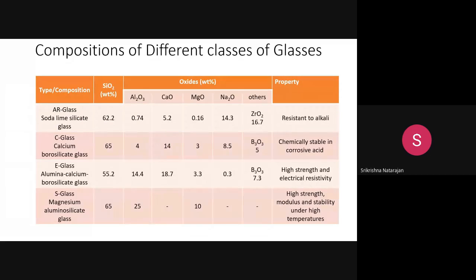And another glass is the S glass, which is called the magnesium aluminosilicate glass. Okay, so here you see this magnesium aluminosilicate. Apart from the silicon dioxide, you have the aluminium and the magnesium. The rest are all absent. So this is for high strength, modulus, and stability under high temperature. Wherever you want to fix a window which should not be easily broken, where high strength is required, in that case you can use this S glass. So there are different glasses with different compositions.